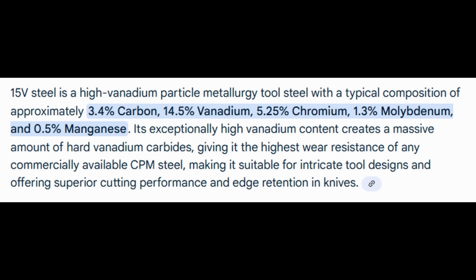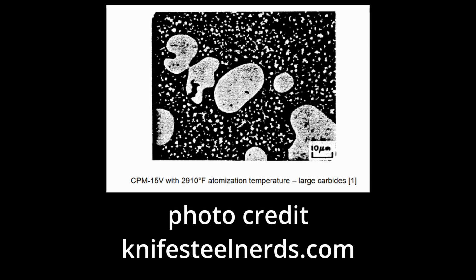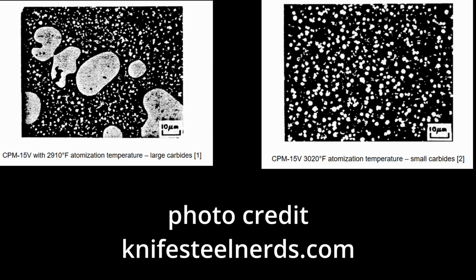However, this super rich vanadium content poses an issue. Metallurgists found that after 11% vanadium, the carbide size would drastically increase because they would form in the liquid steel before the steel could be gas atomized into powder. This is a problem because the larger the carbides being formed, the lower the toughness of the steel. It was discovered that if they increased the liquid steel temperature, it could allow for a higher vanadium content without running the risk of forming those problematic larger carbides. And with this monumental discovery, CPM 15V was born.